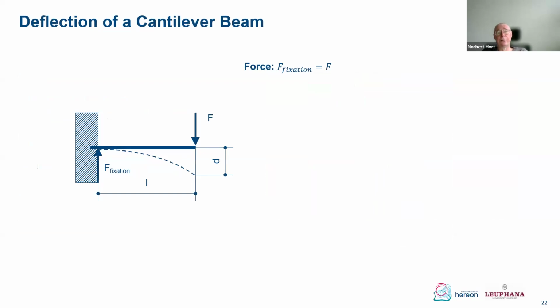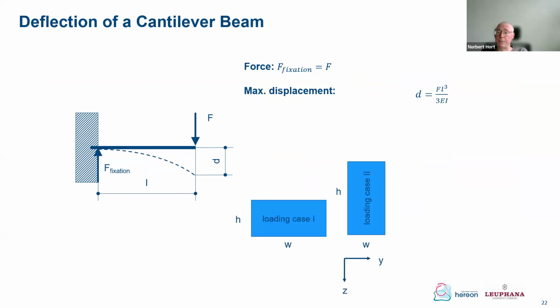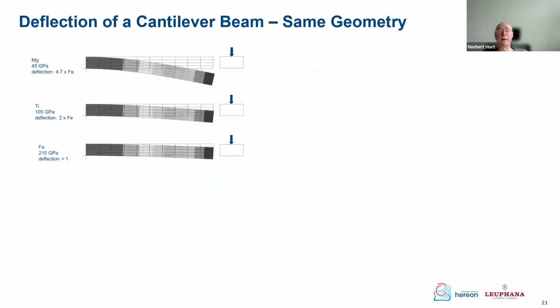And when you look for the deflection, that's also easy. You find this equation, you can calculate it. However, if you look on the maximum displacement of this cantilever, you find only one material parameter, and that's Young's modulus, and the rest is geometry. So look on the geometry. And when you look on the bending, you have to look for moments of inertia. That's also described in these books. Simple equations. And again, it's about geometry.